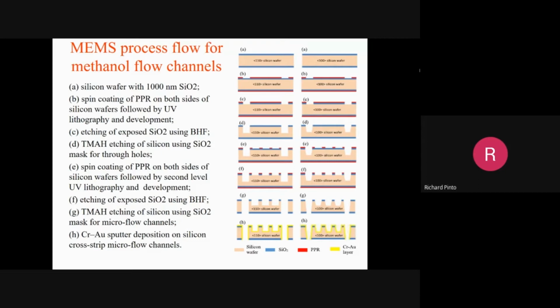You see the through holes, through which methanol, the fuel, gets into the micro channels. Now fuel gets in from the backside of the wafer, not from the front side. The front side is matching with the GDL, as I mentioned in the previous diagram, and the next diagram also shows it. Front side will meet the gas diffusion layer and the catalyst. But on the backside we allow the methanol to get in, so you need the through holes.